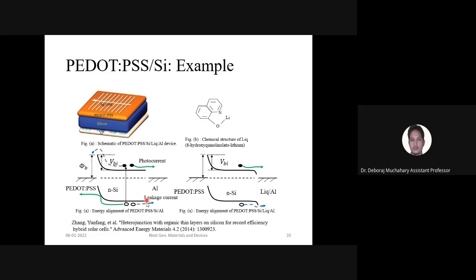And likewise there is some leakage current, that is, if there is some recombination over here between the aluminum and silicon, if the recombination centers are there at the surface, then these holes will be recombining with the electrons, and so it is a leakage current. These dashed lines are leakage current. So this is undesirable current. At the rear surface, if you see this aluminum and this n-type silicon, it has got a smooth path, because the holes can easily pass through, and they can recombine with electrons, and a current will be flowing like this. But due to the use of the LiQ layer here at the rear side,